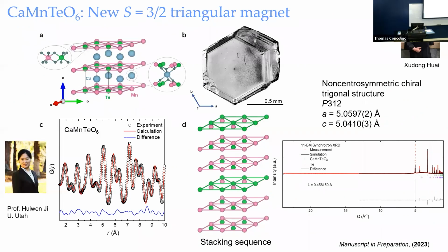So that is where my student Zudong comes in. He created this material, CaMnTeO₆. It is a spin 3/2 triangular magnet, and here is the crystal. So you see it's a two-dimensional spin 3/2 layer, the pink, the Mn here, right? And also tellurium actually on the same layer with manganese. And the calcium in between the layers.